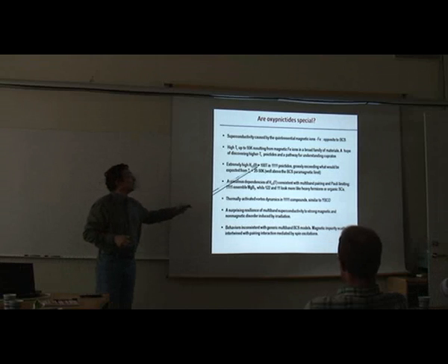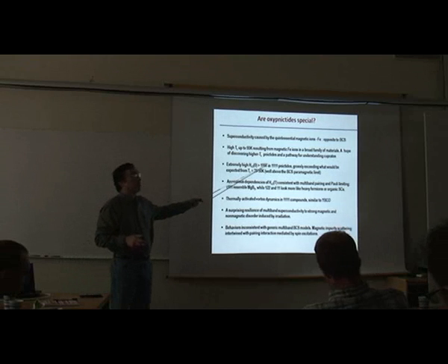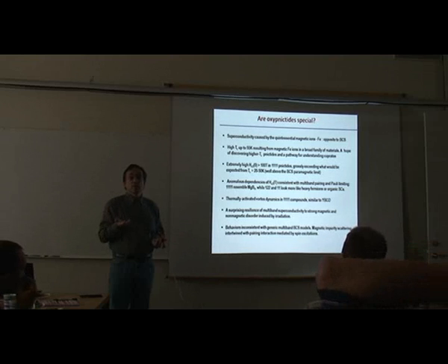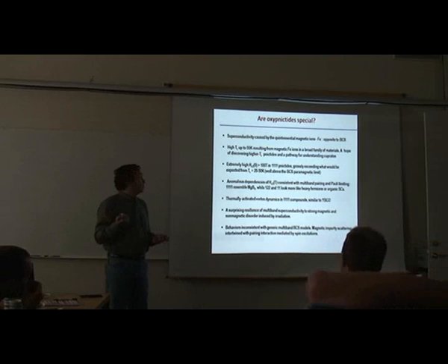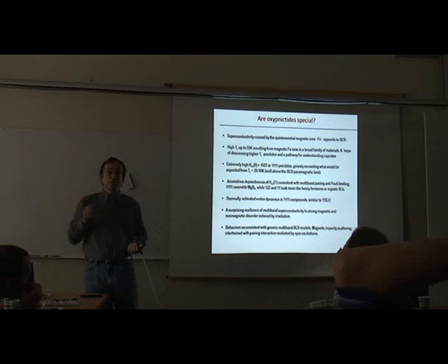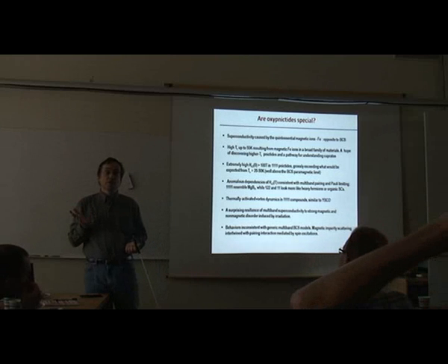So, experimentally, if we see something like around 100 Tesla, and Tc is only 20 Kelvin, that tells us right away that the Zeeman energy is actually much greater than the binding energy of the Cooper pair, the gap. The formula is H in Tesla is 1.84 times Tc in the BCS theory.